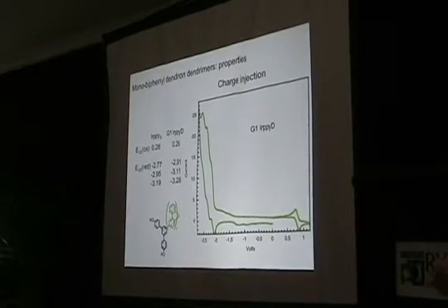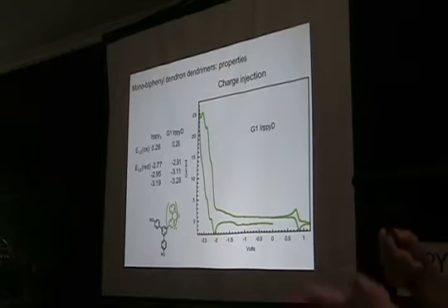Okay, so for this particular dendrimer, with the iridium complex at its core, we see one electron oxidation, and then as we go out, we see 1, 2, 3, and the reverse one's a bit harder to see, 1, 2, 3, so they're kind of elongated flying duck swans perhaps. And so what we can say is that this dendrimer is undergoing one 1-electron oxidation and three 1-electron reductions. Of course, the question is, where do those electrons come from, where do they go to?